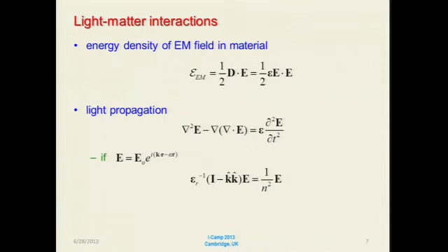We've already seen Maxwell's equations. In a non-magnetic material, you can write it like this. The epsilon tensor is lurking here, essentially determining what happens. Now, if one looks for plane wave solutions of this form, we can rearrange this a little bit. So this is the propagation direction. And what one finds then is we have to solve this equation. And the point I want to stress is that epsilon is a material property, and the refractive index is an eigenvalue. So those are different things. Whereas this thing will change depending on the propagation direction, polarization, and so on, epsilon is what describes what the material does.